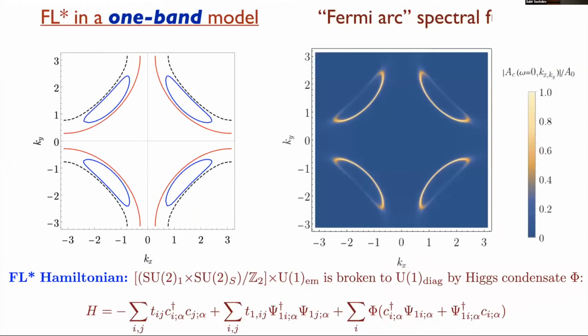So we take first, second, and third neighbor hopping here, and also first, second, and third neighbor hopping there, and the phi. So if you wish, there are 4 free parameters, the T1s here and the phis. The chemical potential you're not free to fix. You fix that, it's important. You fix that to have exactly density 1 on the second layer.